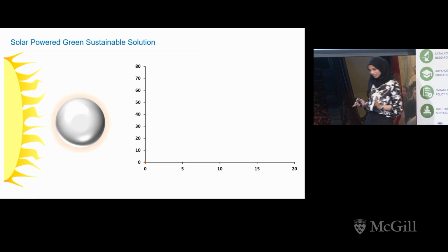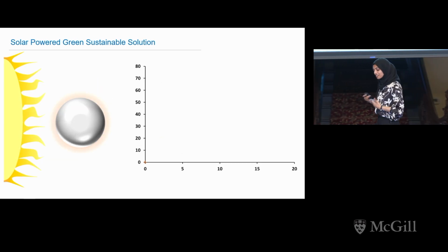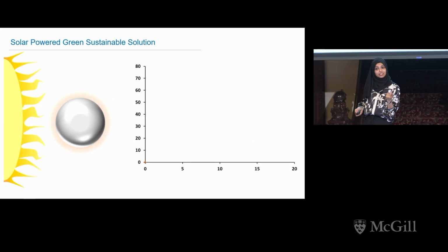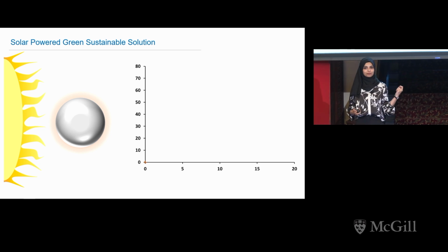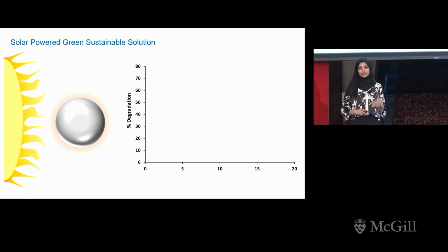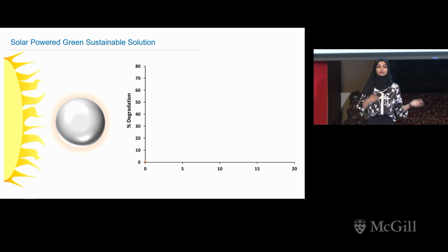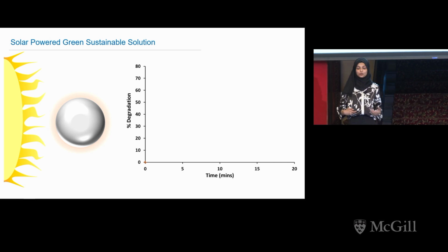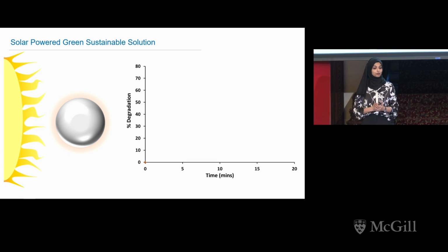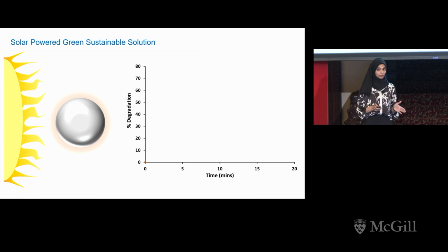And now the big moment: the results for the degradation of a selected contaminant under sunlight using those nanoparticles. On the y-axis, we have percentage of degradation, increasing from left to right. On the x-axis, we have the time needed for these contaminants to degrade. First off, we have a control, which is the photocatalyst alone, and here's how the degradation curve looks.